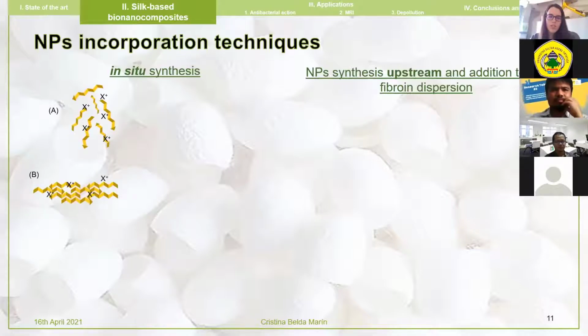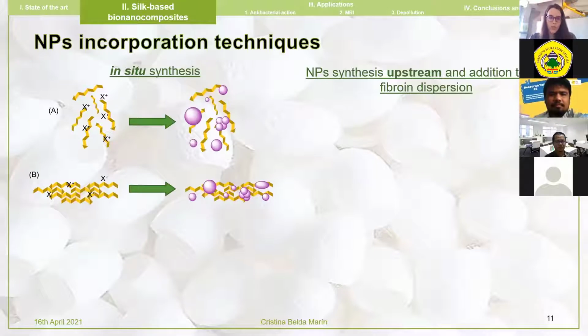So how are we going to incorporate these nanoparticles into silk? The literature has mainly used two techniques, which are in situ synthesis, or the synthesis of nanoparticles upstream and then the incorporation into silk. In situ synthesis consists in synthesizing nanoparticles directly within the silk solution or the silk material. So we are going to add metal ions in our case, and then nanoparticles are formed. This is a very interesting procedure because it takes place in one step.